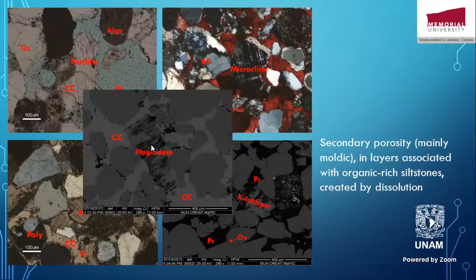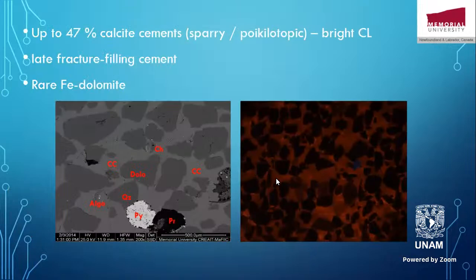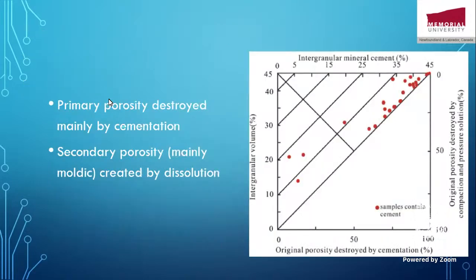Again, we can see here another backscatter diagram with the plagioclase clear here, and this is calcite. You see the replacement of the plagioclase by the calcite. Up to about 47% calcite cements here, and they vary between sparry and poikilotopic calcite, and they show bright CL, as you can see on the right-hand side here. And also, there are late fractures, and they were filled by cement. And there is rare iron-rich dolomite filling some of the fractures there.